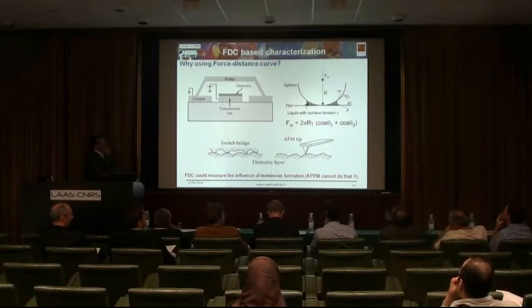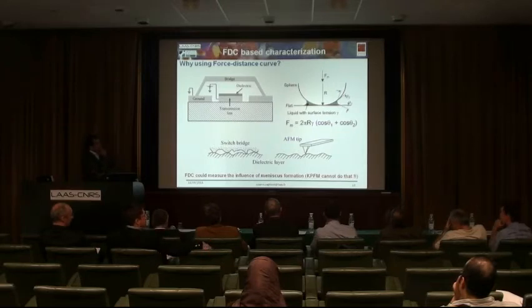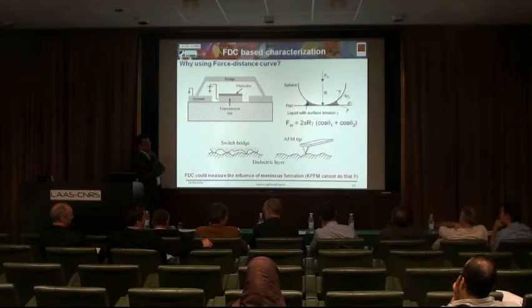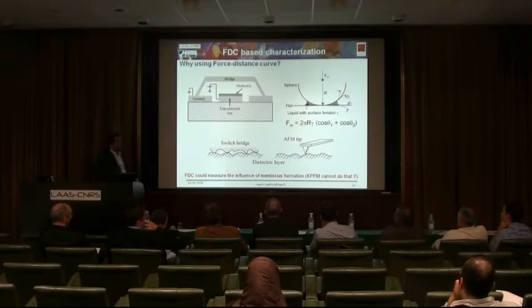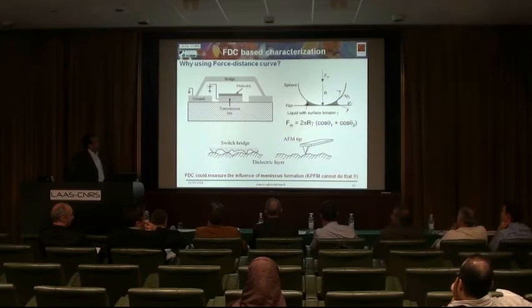I see. Okay, so now at the bottom, you write an expression for the meniscus force. When I look at that expression, the meniscus force is a function of the radius of the asperity, surface tension, and the contact angle. I don't see any influence of the amount of liquid present in this equation. Later in your talk, you found that as you increase the relative humidity, the thickness of the water film goes up, which is responsible for increasing the meniscus force. I don't disagree with your conclusion, but based on this equation, how do you explain that the meniscus force increases as you increase the film thickness?